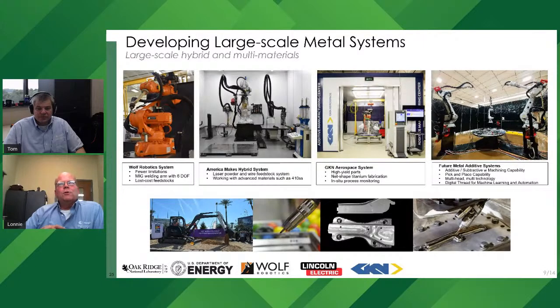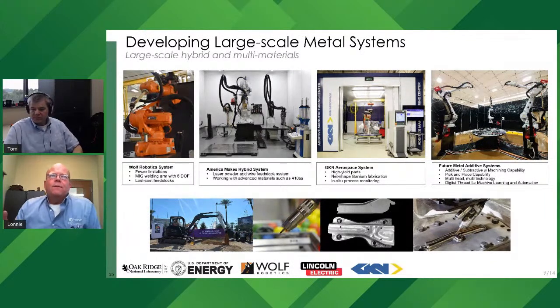So we've had a big push on large scale metal printing. When we developed the BAM, the Big Area Additive Manufacturing, back in 2013 and showed it at IMTS in 2014, at that point in time, most polymer printers made things less than a cubic foot in volume at a few cubic inches an hour. You used a wire as the feedstock. If you look at most plastic 3D printers, you have a filament that you're feeding in. It's expensive. That filament is usually on the order of 20 to 30 bucks a pound.